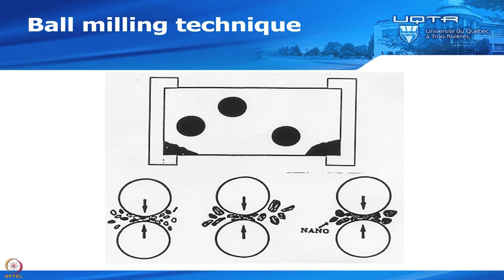So ball milling, very schematically: you have a crucible, and you put your raw material in the form of powder, and you have balls that are made of stainless steel, hardened stainless steel, or tungsten carbide, or some other material. You select the material depending on what you want to ball mill, and you shake this crucible, and then you will have a collision between two particles, or between a particle and the wall of your crucible.